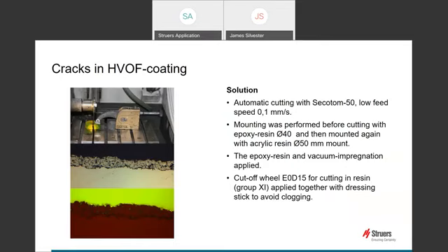For this sample, we used a two-part solution. It was determined that the problem stemmed from incorrect cutting parameters. The cutting was carried out with too high a feed speed. With this being a manual operation, as stated in the previous slide, it was decided to move this cut onto an automatic cutting machine. In addition, due to this sample being very small, the decision was made to use a precision cutting machine, which allowed very slow cutting speeds. In this case, we used 0.1 millimeters per second.